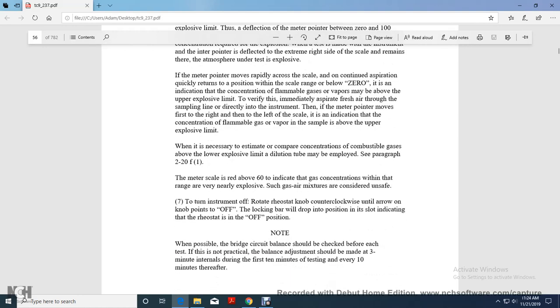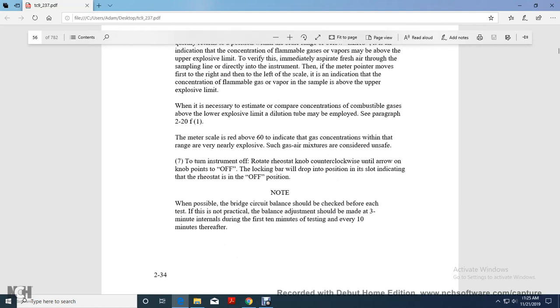If the meter pointer moves rapidly across the scale with continued aspiration and quickly returns to a position below zero, it is an indication that the concentration of flammable gas and vapors may be above the upper explosive limit. To verify, immediately aspirate fresh air through the sampling line directly into the instrument. Then if the meter pointer moves to the right and then to the left of the scale, this indicates that the concentration of flammable gas or vapor in the sample is above the upper explosive limit. When necessary, estimate the combustible gas concentration above the lower explosive limit with the dilution tube that may be employed. Meter scales reading above 60 indicate the gas concentration within the range is very nearly explosive. Such a gas mixture is considered unsafe.